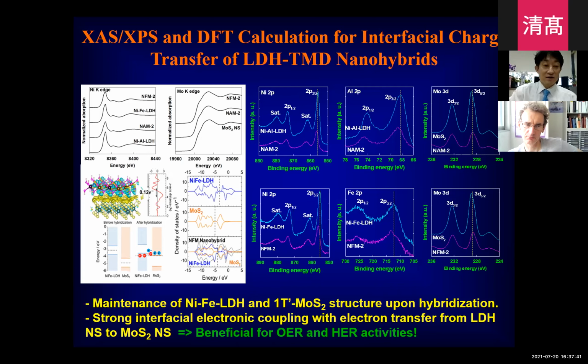Compared with XANES, XPS is more sensitive to the interfacial charge transfer. So from the XPS analysis, we observed the slight charge transfer between molybdenum sulfide and LDH. It is confirmed by DFT. It's very noisy. There is a lot of thunder. Anyway, from the DFT calculation, we can confirm the significant charge transfer between the LDH and molybdenum sulfide. Actually, electrons migrate from the LDH to molybdenum sulfide. So it is valuable to enhance the OER activity of LDH and the HER activity of the molybdenum sulfide.